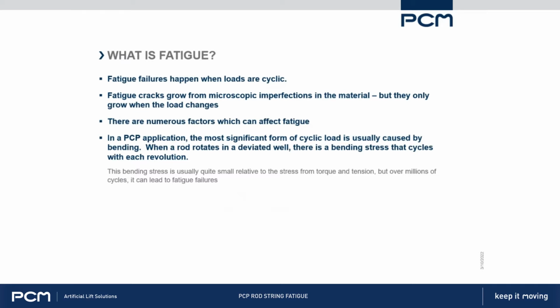So that's causing a cycle. That bending load is generally very small in a PCP application. Typically about 2% of the total stress on the rod is the bending stress. In a really extreme case, it might get as high as 10%. So it's small compared to the stress that's from the torque and axial load on the rod, but over millions of cycles that can lead to fatigue failures.